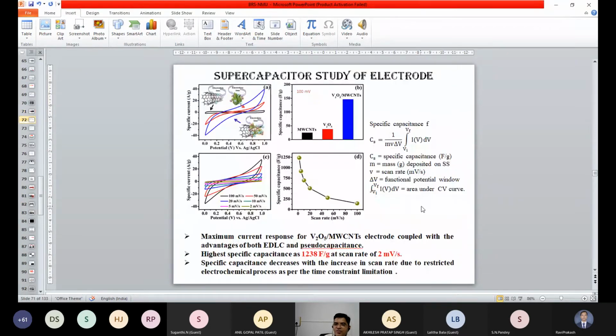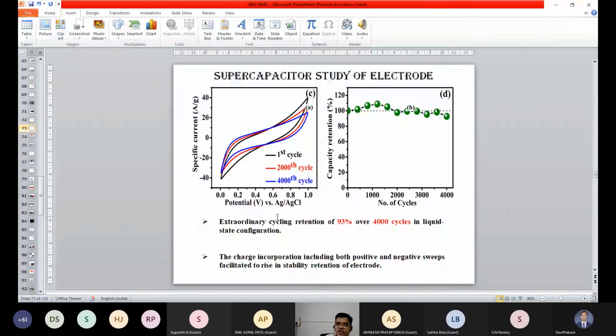through the HRTEM analysis. Then again we have calculated the specific capacitance, and for vanadium oxide, interestingly, the specific capacitance goes up to 1238 farad per gram. This is a very high value reported, 1238 farad per gram, meaning for 1 gram it gives a specific capacitance of about 1000, which is a very high value. Not only this, we have studied this for 4000 cycles. It also shows stability of about 93%, right, in the liquid cell.